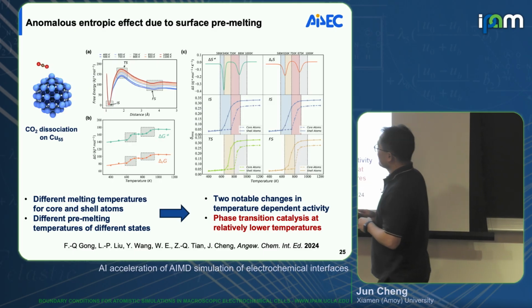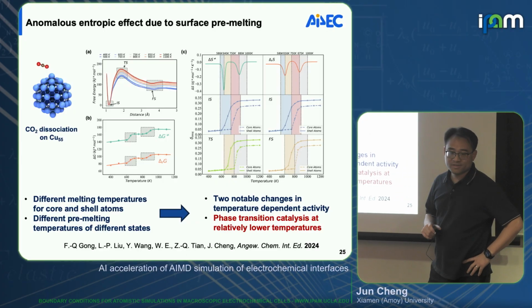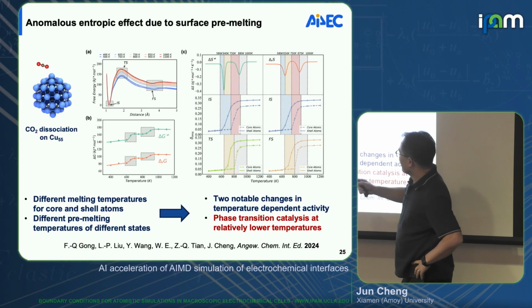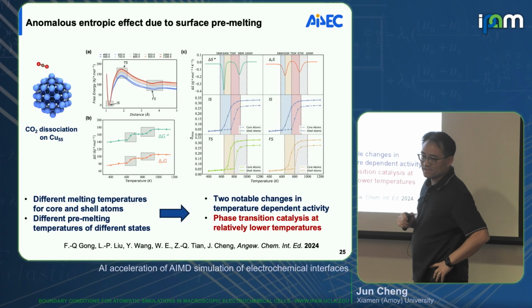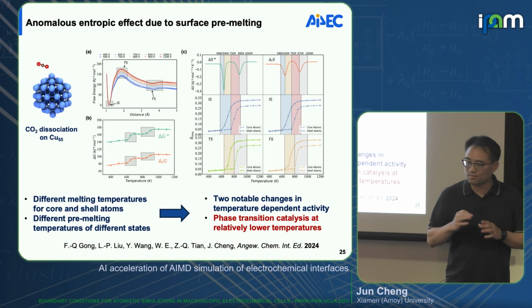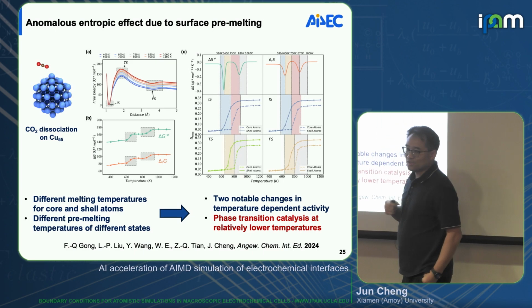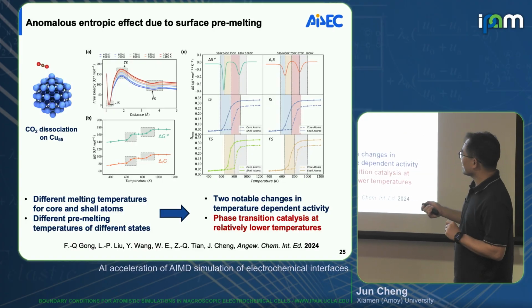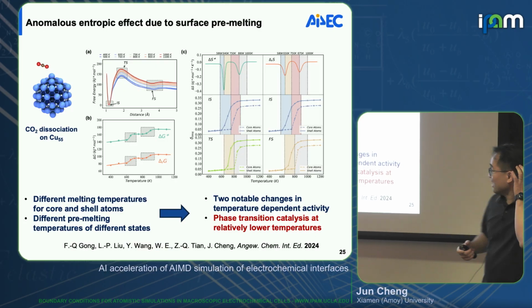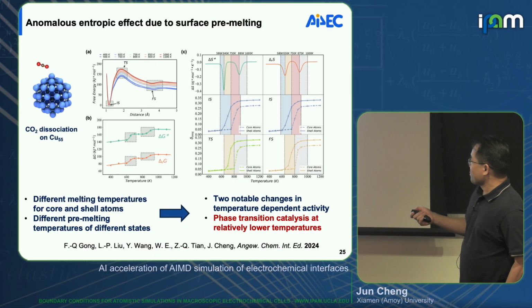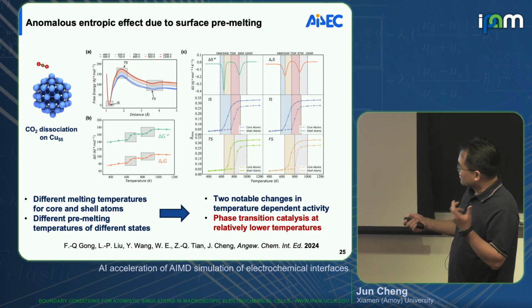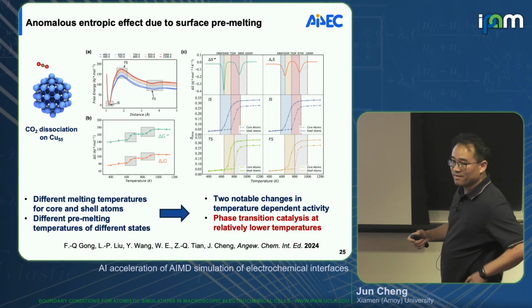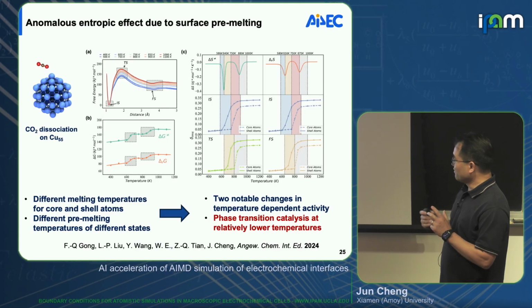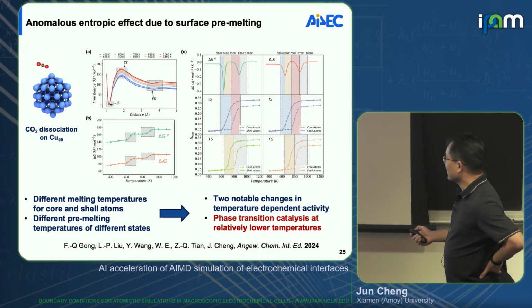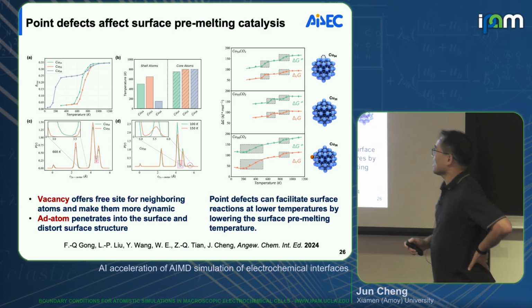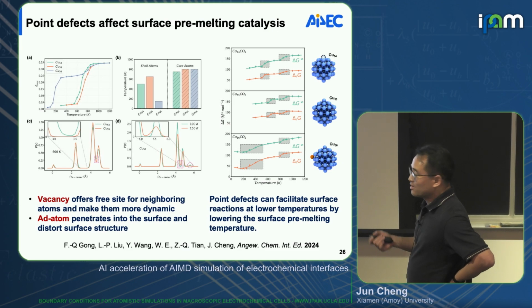catalysis behavior. The model system is CO2 dissociation on Cu55, so it's 1.5 nanometers. You can see there are two jumps in the free energy profile, similar to what we calculated, but two jumps. It turns out the first jump is actually due to the surface melting, and the second jump is due to the core melting. So you can really see that the change of the adsorbed state can already change the phase behavior of the surface layer of the metal nanoparticle, which can directly contribute to the catalytic effect.